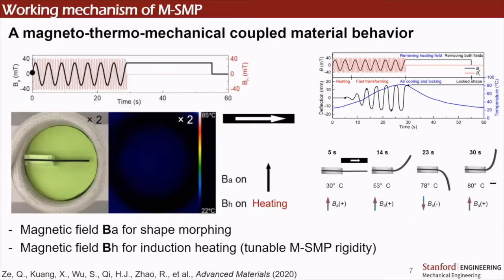Again, we still want to do everything untetheredly, right? So we use a magnetic field to control the shape morphing, and we also use a magnetic field to generate heat. The concept is that we apply a coupled magnetic field. The black curve that we see over here is for shape morphing. We're just applying an up-down magnetic field to trigger the beam bending of this strip. And the red curve is a high frequency alternating magnetic field to trigger magnetic hysteresis loss for induction heating.